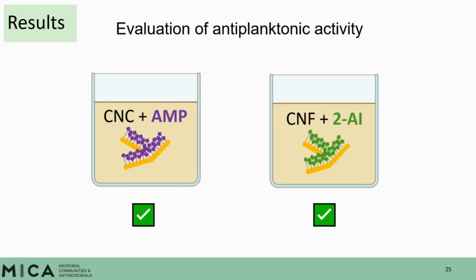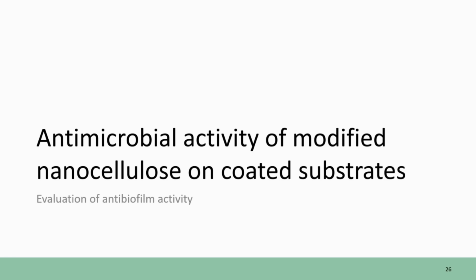So we tested three types of nanocellulose, CNC, CNF, and BNC, modified with the AMPs and the 2AIs at different concentrations, and based on our results, the most significant activity in suspension was CNC modified with the AMP at a specific concentration, and CNF modified with the 2AI at a specific concentration. So we used these combinations to proceed to work package 2, which is the assessment of the antimicrobial activity of the modified nanocellulose on coated substrates.